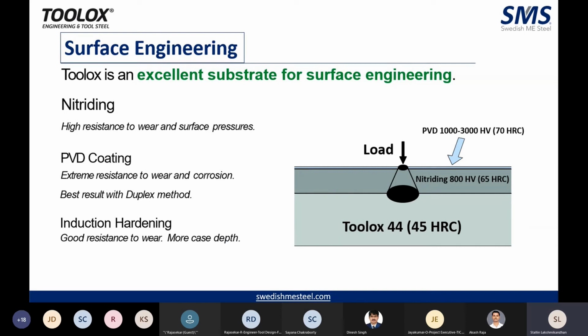Now, let's look at the different surface engineering that can be done with Toolox 44. As we had already discussed, Toolox is available at 45 HRC. So if I require my material to be at 58 HRC, 60 HRC, or 65 HRC, what am I to do? You have different processes. Of course, vacuum heat treatment is ruled out, as it is already heat treated material. You can do whatever surface treatment is possible on the material. So you have nitriding, PVD coating, induction hardening, and also laser hardening.